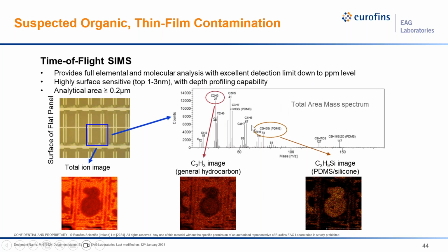And then for people that do time-of-flight SIMS, or a lot of types of SIMS, you can become somewhat of a barcode scanner and start to jump out and see peaks at 28, 73, 127, 147 are all peaks associated with silicones, polydimethyl siloxane, PDMS. So you can kind of collect those, map them out, do the same thing for the hydrocarbons. So you can get maps of chemistry on the surface, and then likewise pull the spectral data from each individual area that you'd like.